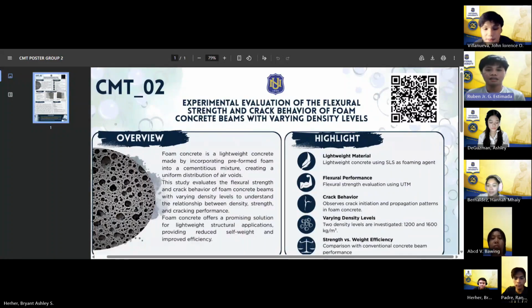This study investigates the mechanical performance of lightweight foam concrete integrated with sodium lauryl sulfate, or what we call SLS, as a foaming agent, specifically focusing on its flexural strength and crack behavior. By evaluating beam specimens at target densities of 1,200 and 1,600 kg per cubic meter, we aim to determine how varying density levels and curing ages of 7 days, 15 days, and 28 days influence structural integrity compared to conventional